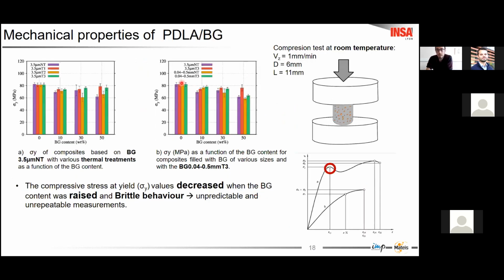We studied the mechanical behavior of these composites using a compression test on cylindrical samples, and we followed the evolution of the stress at the yield strength as a function of the filler ratio, the bioglass content. We observed that as the filler ratio increases, the stress decreases, and the sample becomes more and more brittle, as shown previously in literature.